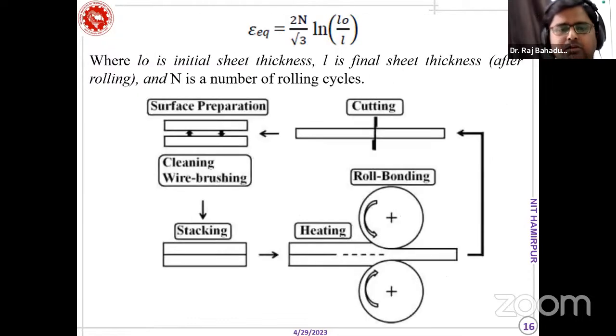Coming to the ARB, in this technique, it's very simple. You all understand the rolling process. We have two pieces of sheet, and we stack them together by cleaning the surface, and at a certain temperature we roll that material, reducing the area by 50%, and again we have a similar thickness to what we started with. If you keep on repeating the deformation by this technique, you cut it and stack together, and again you deform it. So a number of cycles we can repeat.